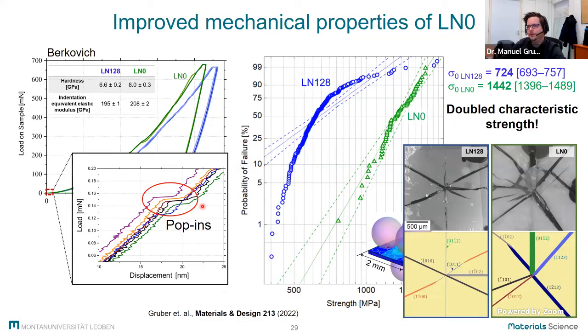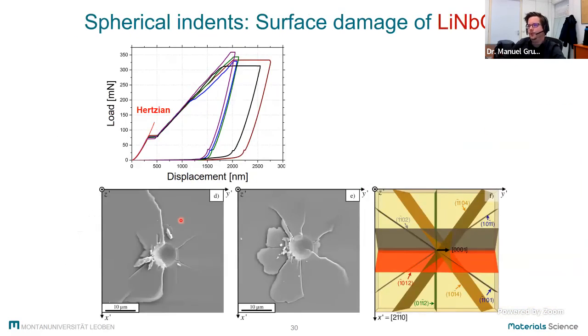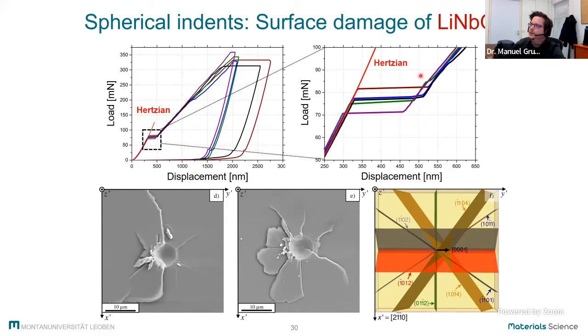And then we wanted to have a look if there is some kind of plastic deformation going on in our specimens. Since the Berkovich indenter has edges and will therefore promote fracture and plastic deformation in certain directions, we moved on to spherical indents and started with large imprints to get a first feeling for what's going on in our single crystals. And there we could see that, again, we activate the same cleavage planes for our large imprints. Nevertheless, we wanted to see what's going on exactly at this very first point of plastic deformation.